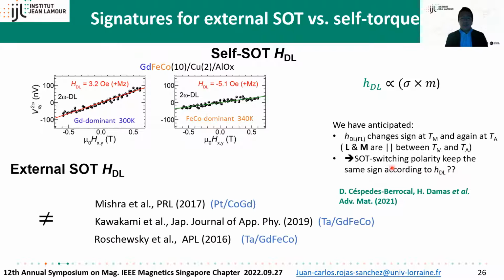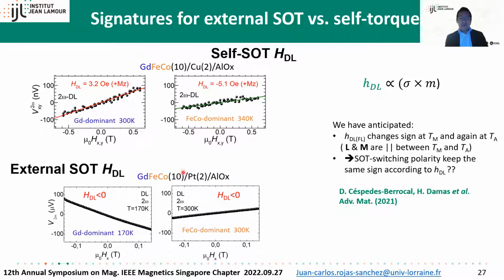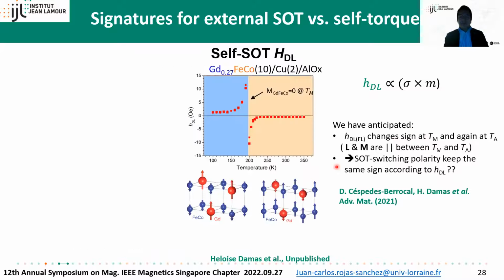So that's what we can observe. Look in the literature, and you will find that this behavior is totally different. Actually, let me show our own data here. This is a bilayer gadolinium iron cobalt platinum. Here, at gadolinium dominant temperature, we have one slope, and at iron cobalt dominant, we have the opposite slope. We can see that this behavior is different than this. So that is according to what we have anticipated and proved in this report.